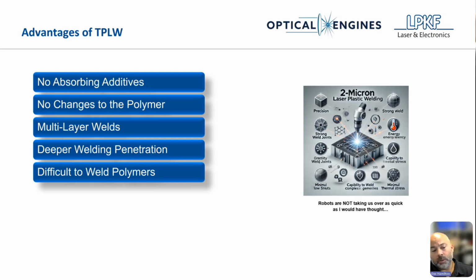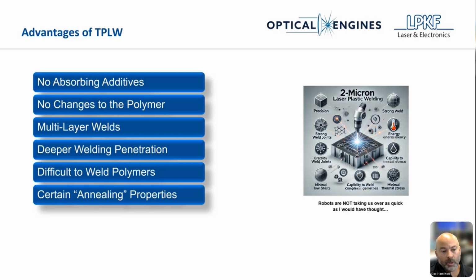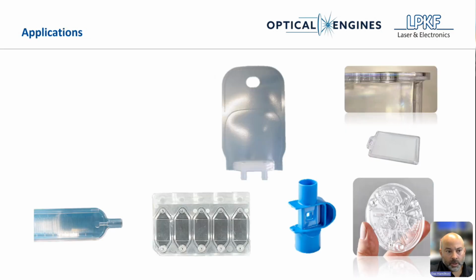You can weld difficult to weld polymers. This is kind of a traditional carryover from through transmission welding, where let's say we have a clear to a white, where the white material tends to refract quite a bit of the laser energy and can burn. 2-micron in some cases actually works better, even in a format of optically clear or IR clear to absorbing. It also has certain annealing properties, which I think we'll cover a little bit later, where it can more or less soften or relax the plastic from inherent stress and avoid any cracking afterward.